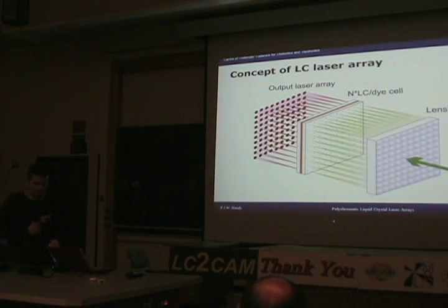The other problem with conventional lasing is that the high amount of energy being focused into the single spot can actually cause reorientation of the liquid crystal through alignment with the optical field of the pump laser. This also can lead to localized heating, localized expansion, distortion of the helix, and then it has a detrimental effect on the lasing. So our idea was to replace our single focusing lens with a lens array.